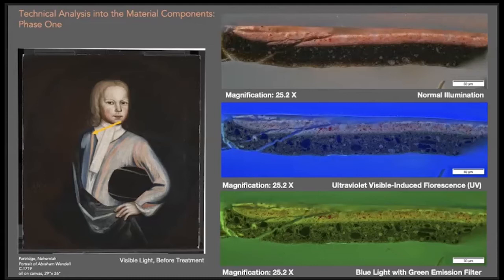While the samples are small, we've been able to gain an immense amount of information from each sample. This one here shows the presence of Red Lake as identified by both its warm fluorescence in the UV image, but also the color and shape of the pigments. Through analyzing these samples, we have found that Nehemiah Partridge's preparation of the Red Lakes varied throughout the paintings. For instance, the Red Lake used to create the modeling in the sitter's costume was here mixed with lead white in order to give more body and opacity and create a pink shade.